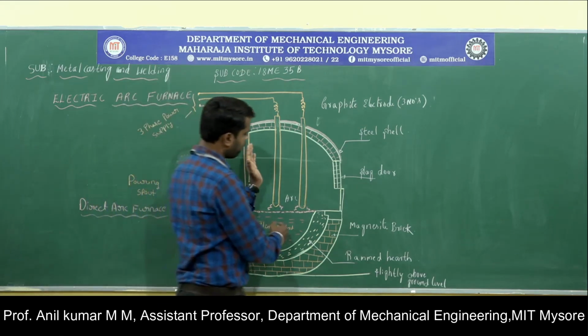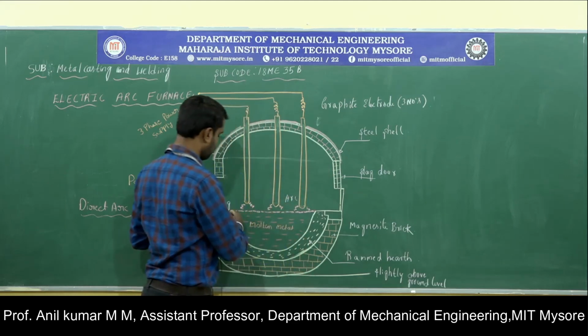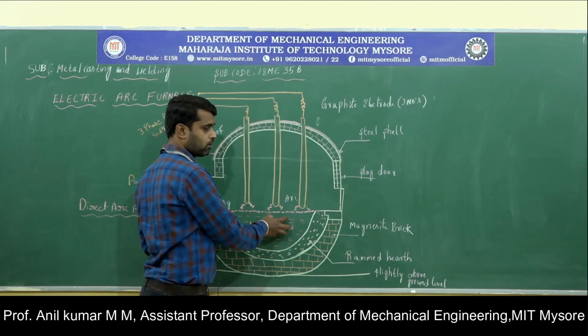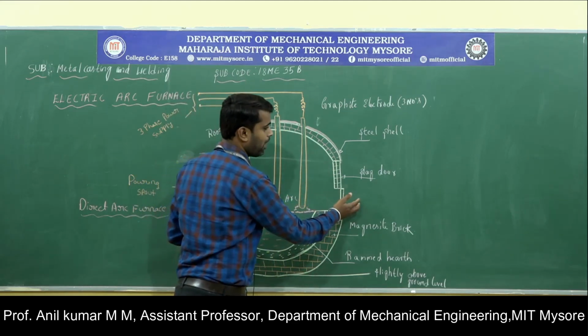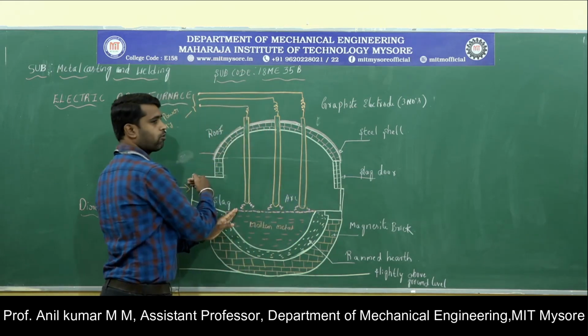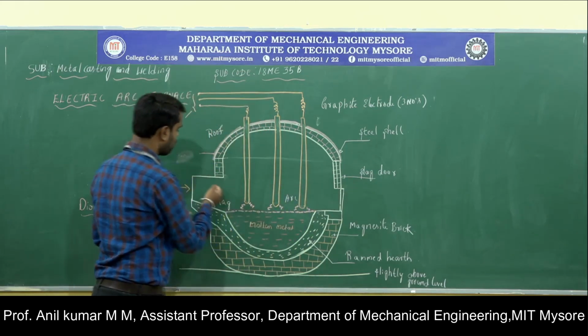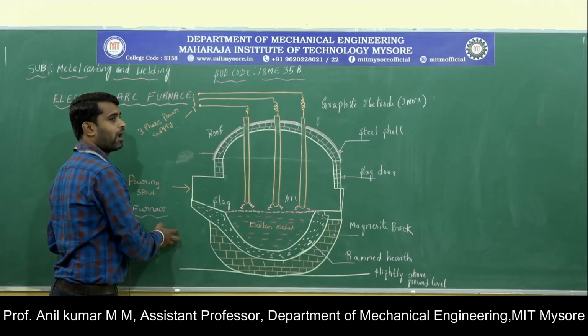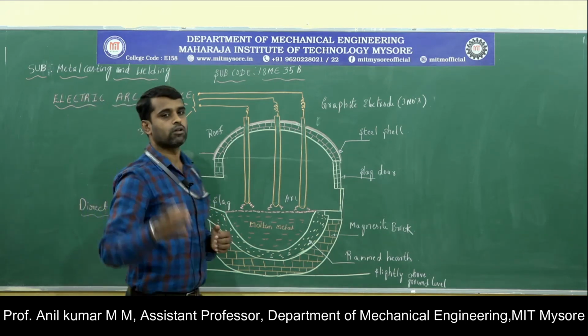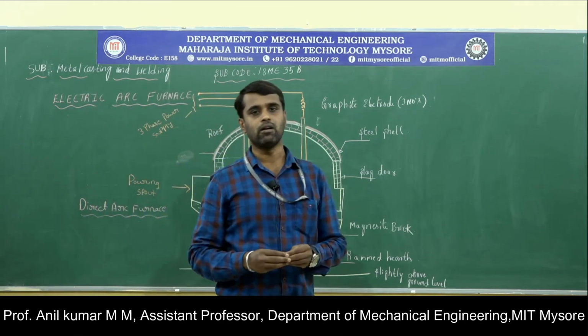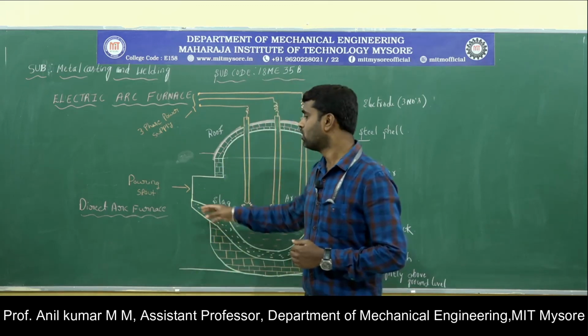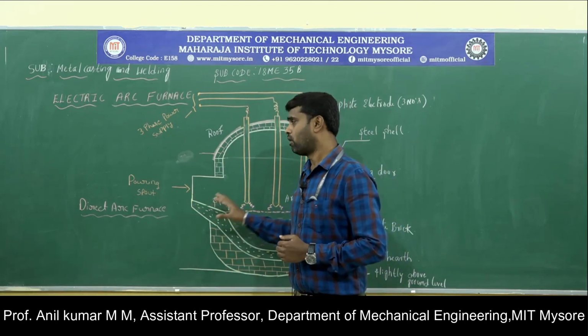Okay, when you tilt the furnace in the backward position, we can remove the slag present on the molten metal, and after removing the slag we can tilt the furnace in the forward position and pour the molten metal into the ladle, and that molten metal can be poured into the mold cavity and we can prepare the casting. Okay, that is the working of the electric arc furnace.